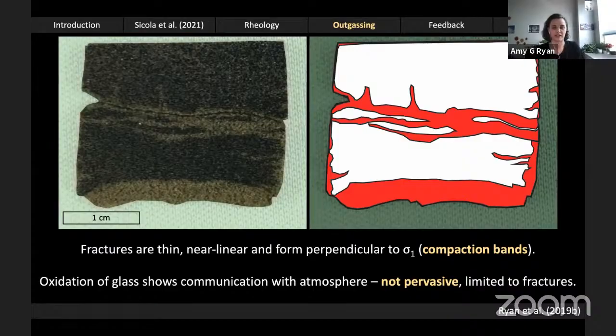The oxidation of the glass also shows that when a fracture forms and the CO2 is expelled and the atmosphere is imbibed and thus oxidation occurs, that's limited only to the fractures. It's not a pervasive process. We don't have whole-scale outgassing of the material as a result of fracture formation. And this really indicates how inefficient outgassing by melt fracturing can potentially be.